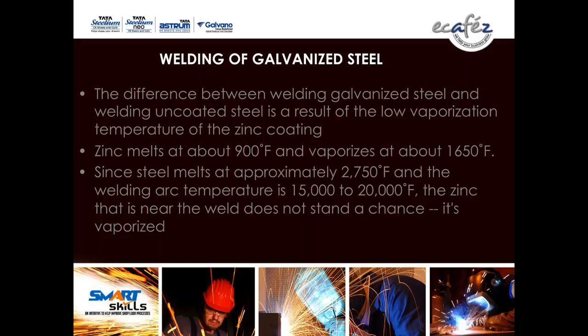The difference between welding galvanized steel and welding uncoated steel is a result of the low vaporization temperature of the zinc coating. Zinc melts at about 900 degrees Fahrenheit and vaporizes at about 1650 degrees Fahrenheit. Since steel melts at about 2750 degrees Fahrenheit and the welding arc temperature is 15,000 to 20,000 degrees Fahrenheit, the zinc that is near the weld does not stand a chance. It's vaporized.